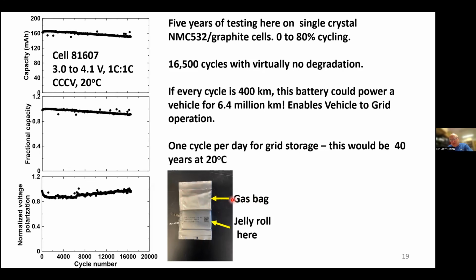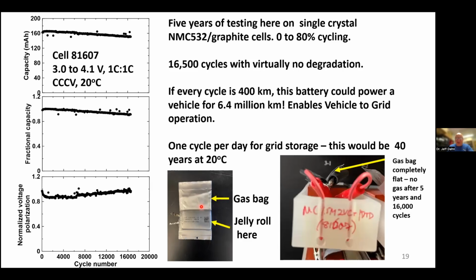So we're going to take a view in along this arrow and take a look at this gas bag to see if it's puffed up for this cell. So this is the cell number 81607. And here's the gas bag sort of curled vertically. You're looking in at the direction of this arrow, and it's absolutely flat after 5 years and 16,000 cycles. So that means virtually no degradation in the cell at all. It's incredible.